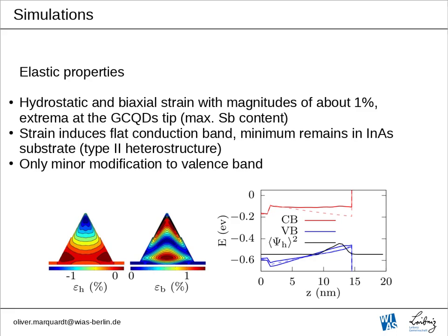So let's have a look at the elastic properties of the system. What you see on the left side are hydrostatic and biaxial strains, and both of them exhibit a maximum of about 1%. For the hydrostatic, clearly at the top of the cones, which is not too surprising, first of all, because it's the top of a cone, so of course elastic relaxation is strongest there. And second, it has the maximum antimonide content. And for the biaxial strain, we see maxima also at the top, but also on the very bottom where the arsenide content is largest.